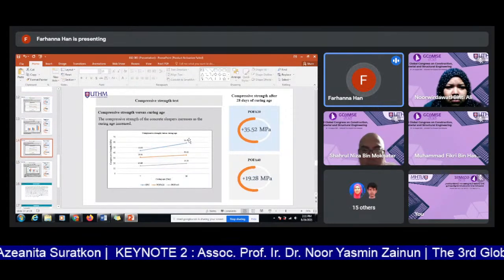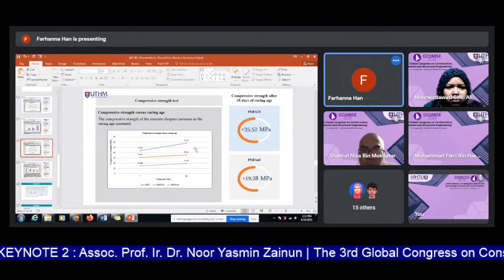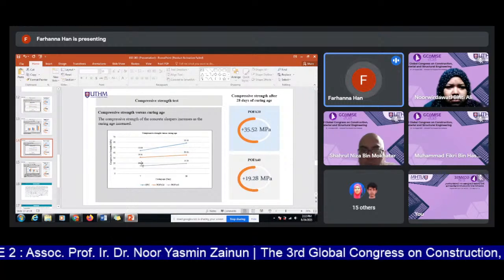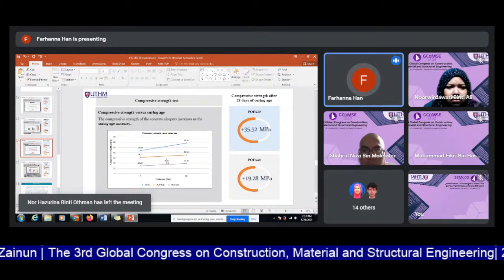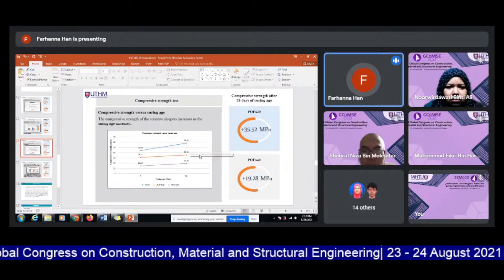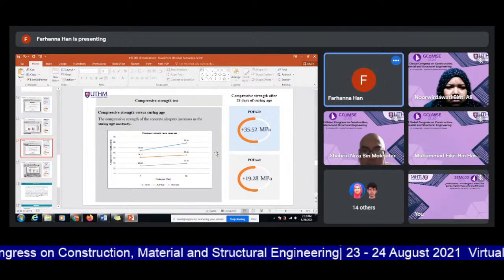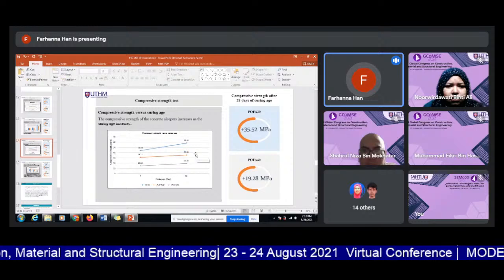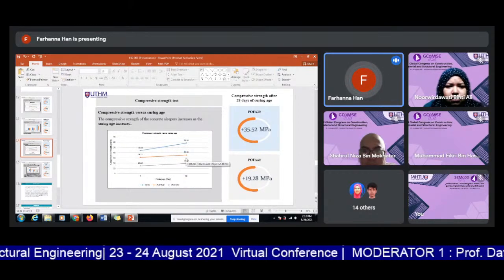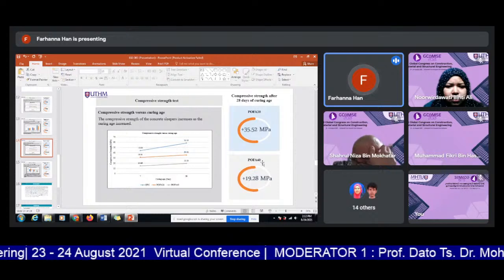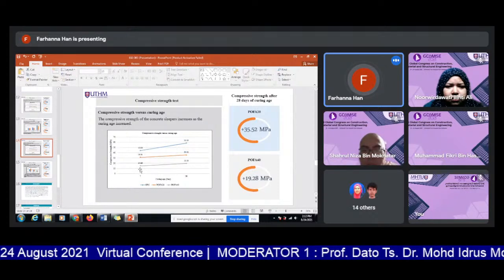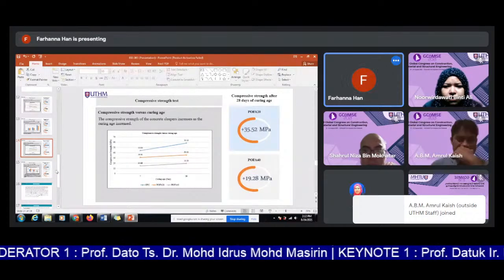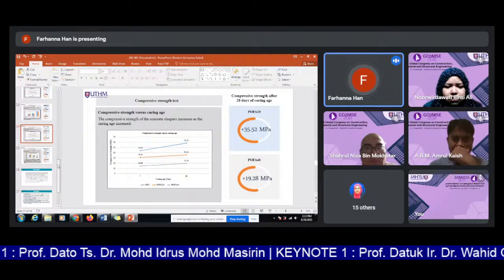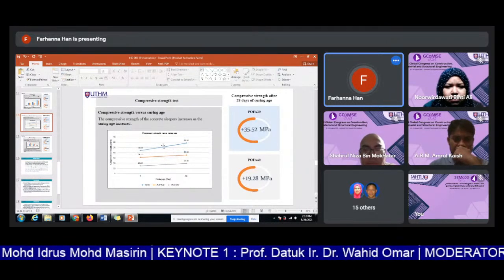Next, this is the result from the compressive strength test. This is the compressive strength versus the curing age. As the curing age increases, the compressive strength of the sample also increases. For POFA 20, the compressive strength increased by 35.52 megapascal from 7 days to 28 days of curing age. And for POFA 40, the compressive strength improved by 19.28 megapascal along the curing age. This shows the pozzolanic reaction between the POFA and the cement along the curing age.